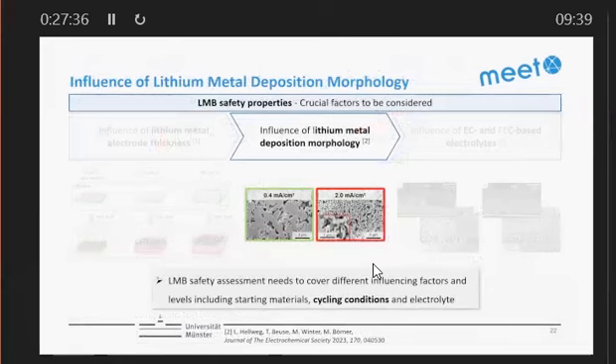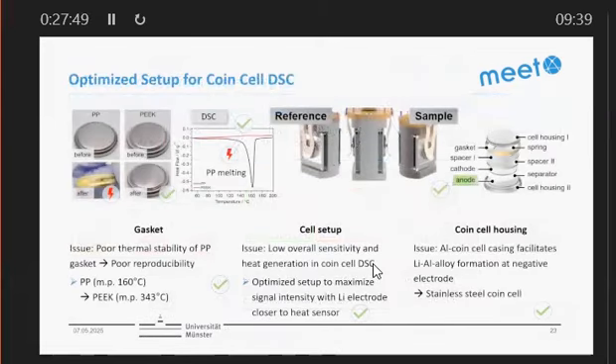Okay, now we are coming to the influence of the lithium metal deposition morphology. And of course, this is nothing surprising here because, of course, at higher current densities, you have more high surface area lithium. But let's go for it and see what we learn. One thing we learned is it does not work. We did not get any reproducible results. What was the reason? Okay, when you buy a coin cell, then you buy the typical coin cell. It is either aluminum or stainless steel. And then you put it together with a sealing. And this sealing usually contains polypropylene.